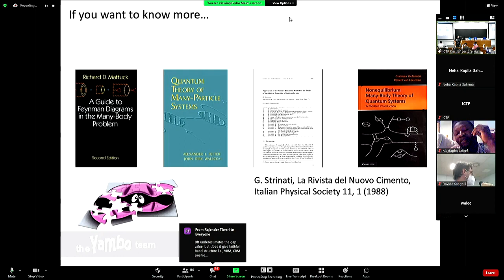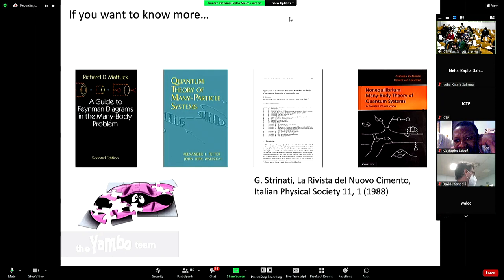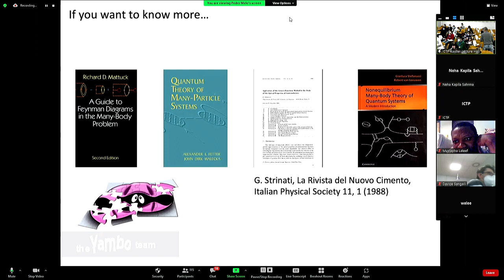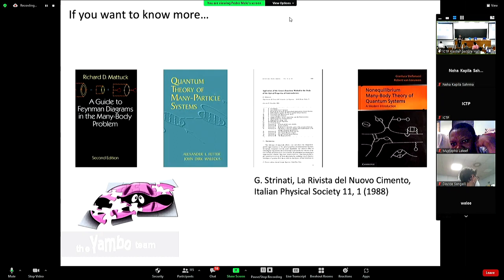Ab initio many-body perturbation theory is parameter-free: you don't feed it any fitted parameters. There are numerical convergence parameters — energy cutoff, number of bands — but these are the same as in numerical integration; they are not fitted to experiment. For the second question about differences of gaps: even for differences, you still need to go to GW, because there is no guarantee that the DFT difference will be accurate. For example, the GW correction to the gap of transition metal dichalcogenides is on the order of 1 eV, which is enormous, and similar for hBN — so DFT differences at an interface will not be reliable.